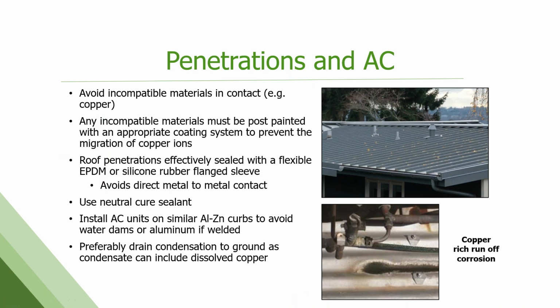So avoid incompatible materials. Again, lots of technical bulletins on this, on what you can and can't use. Any incompatible materials should be painted to prevent that direct contact. You get a nice inert barrier in between, which helps mitigate that. Seal it where you can. Use a neutral cure sealant. Again, there's a tech bulletin just on sealants available. We want to install AC units on similar aluminum zinc curbs to avoid water dams, or aluminum if it's welded. Make sure drain condensation doesn't have dissolved copper in it. Here's an example where some copper from these pipes was leaking and draining onto a Galvalume roof, causing pretty severe corrosion and oxidation.